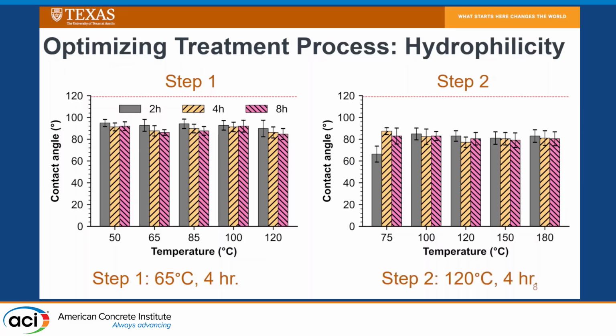And the best exposure time and temperature range in terms of really looking at reducing the contact angle measurement was 120 degrees at 4 hours. And again, she did a lot of work prior to doing this with different chemicals, and this was like the best combination. So the final two-step process here was looking at using 65 degrees Celsius at 4 hours for the first step, and then the second step was using 120 degrees for 4 hours.